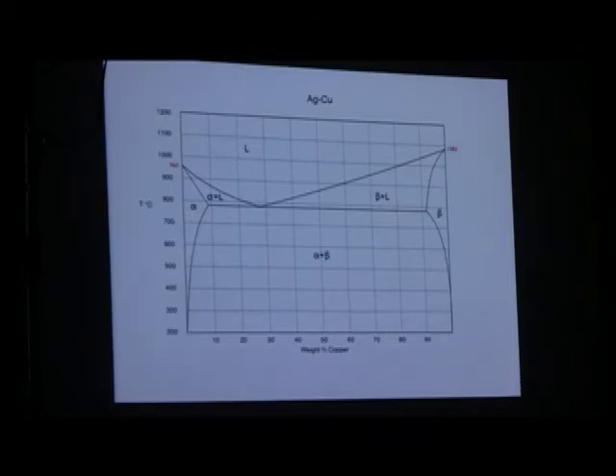The little Greek letters there indicate phases or crystal structures, different crystal structures. Silver copper forms two distinct crystal structures, one they call alpha, one they call beta. Most of the silver that we work with is majority alpha because it's very high in silver content, but there is a trace amount of beta in there. This is what makes sterling silver harder than silver or copper alone. You have two different crystal structures. They don't mate well together, so it makes it more difficult for the metal to be moved because these different sized crystals don't want to slide across each other easily.